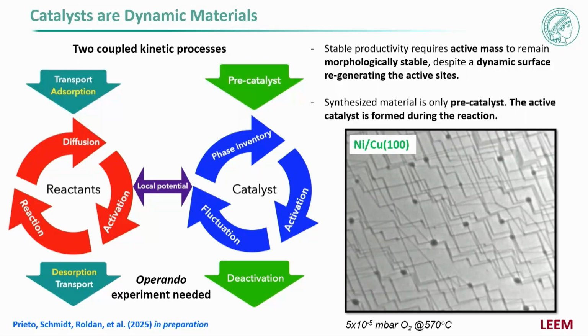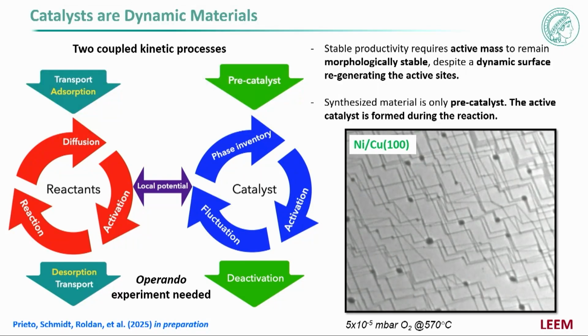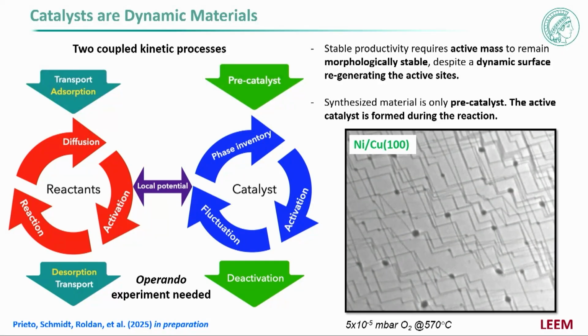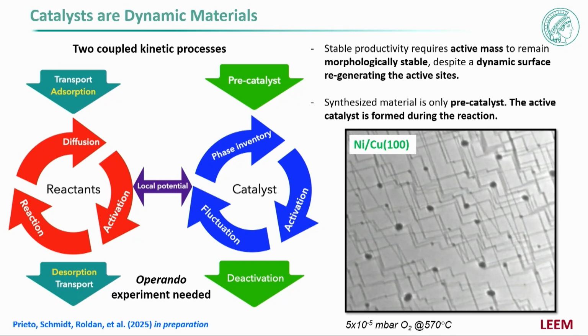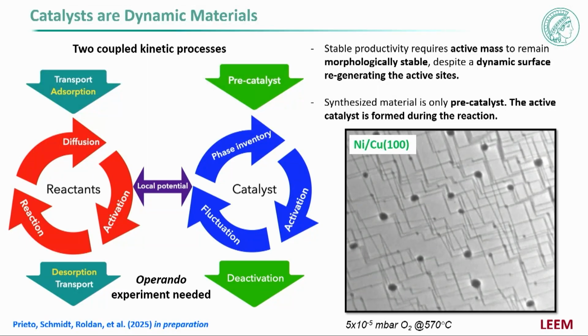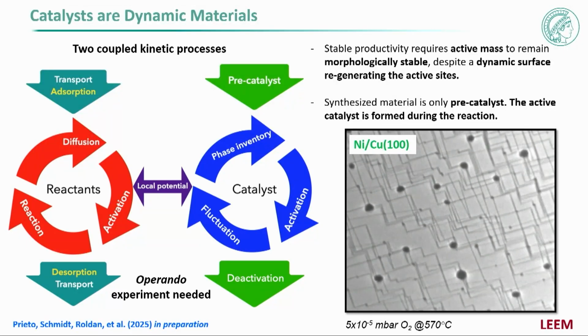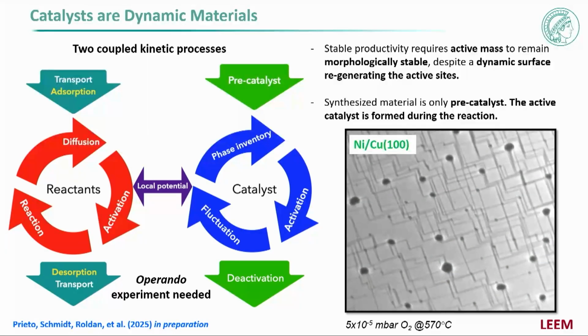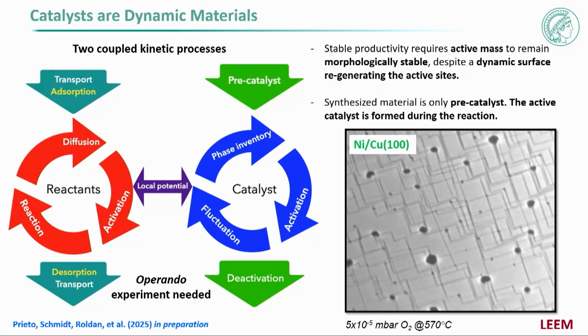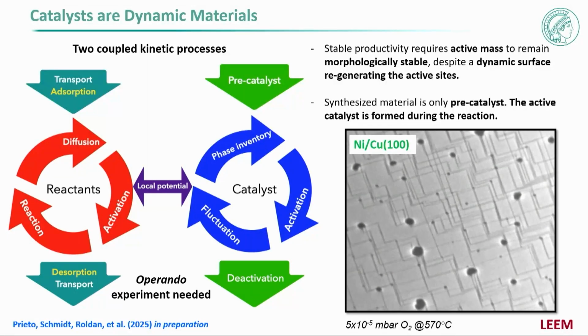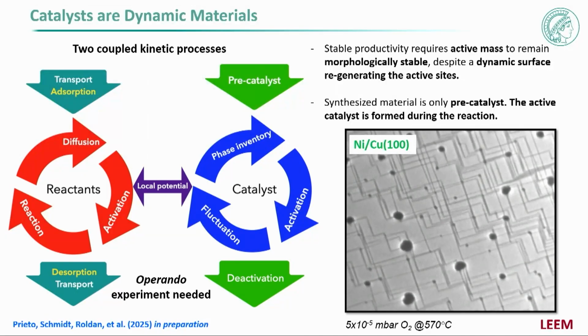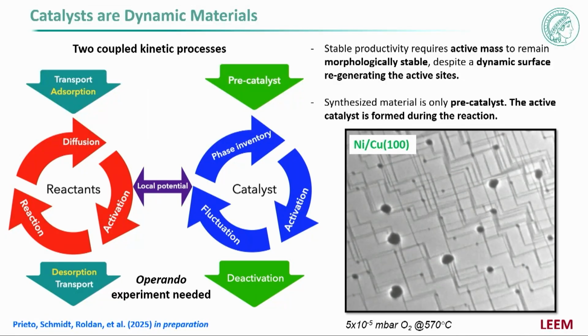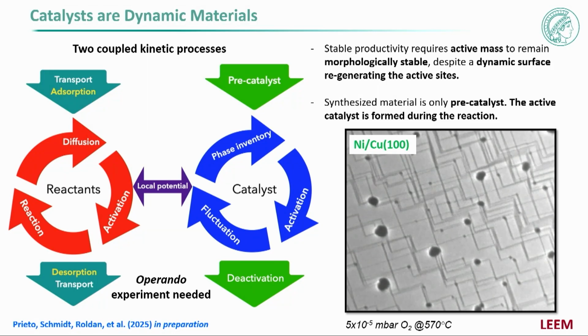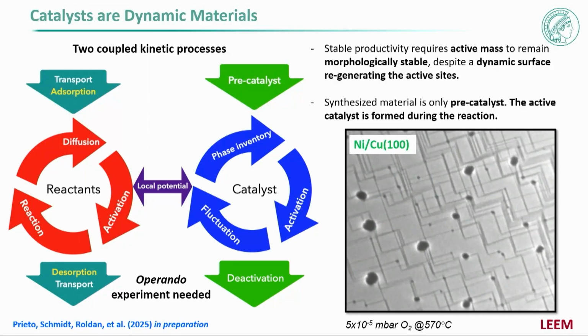I put a video here because I think it illustrates very nicely. This is transmission electron microscopy, and it's going to show you how a catalyst is changing. This is a catalyst that we can use to make green methanol. You combine CO2 and green hydrogen, and you can make methanol. Here, these are nickel particles. The rest is a copper surface. And you see these things moving here, right? This is bad, because we only have some temperature and a very small amount of oxygen, and you see that these are atomic steps, and these atomic steps are already changing with this minute amount of oxygen at a certain temperature.